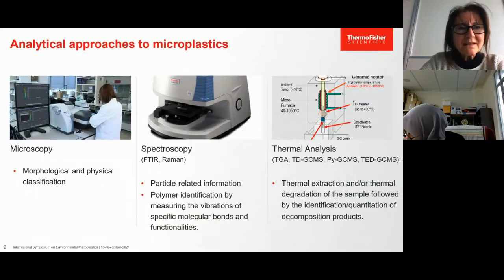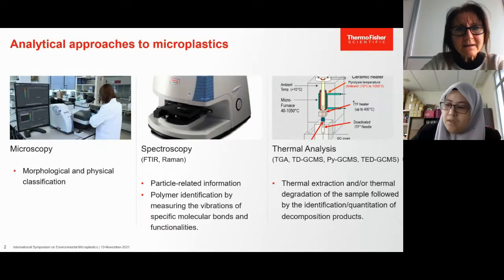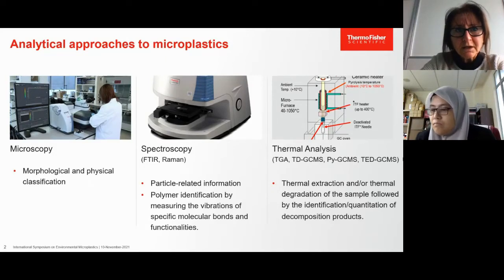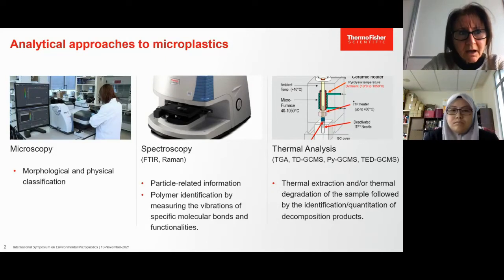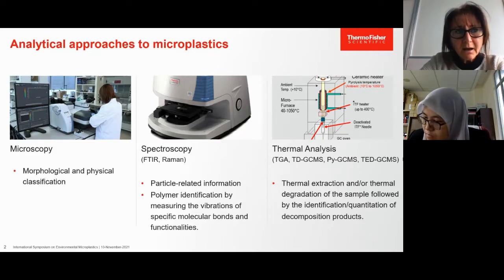So I was saying that those techniques, microscopy and spectroscopic techniques, can assess the level of microplastic contamination based on particle-related information like particle numbers or through imaging approaches. Typically, those techniques allow the determination of microplastics down to a size of about 10 micrometers for FTIR and less, down to 1 micrometer, with the Raman.